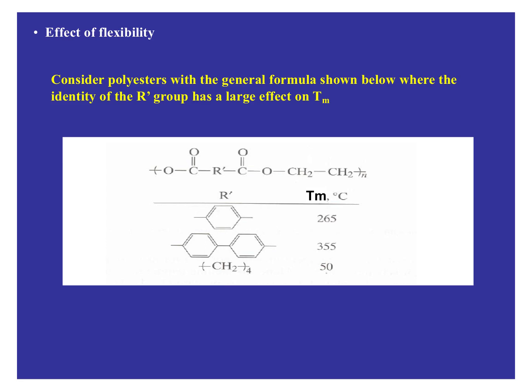And if we look at flexibility, we can also look at these R groups as well. And so we plug in R prime here in this particular structure, so we're basically messing around with the initial PET structure where we have a melting point of 265. We put in 2 of those, it goes to 355. That should make sense. All right, it takes more energy to get these big, bulky phenyl groups out. There's 2 of them. All right, it's going to take more energy. We instead get rid of the phenyl groups entirely, and it drops to only 50.